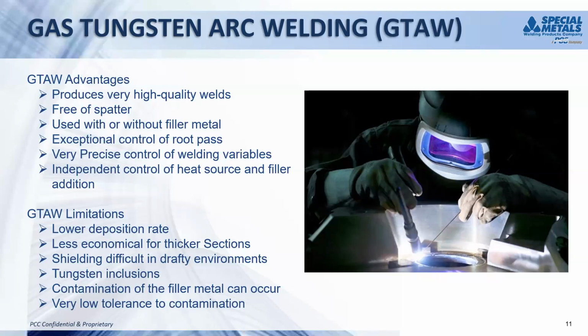They're just going to kind of be pushed around, and eventually they're going to go to the sidewall and become an inclusion. That's just a side note on this. One of the big problems with the floaters or the inclusions, the better you are at doing mechanized TIG welding, the bigger problem they can be. Because as you get very precise in control of that with the mechanized process in TIG, the floaters tend to go to the same spot and they tend to deposit on the same side of the weld bead.